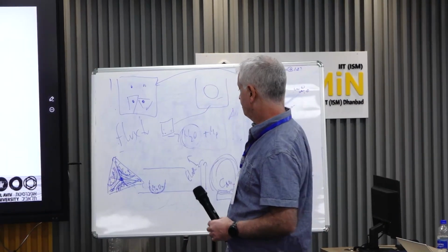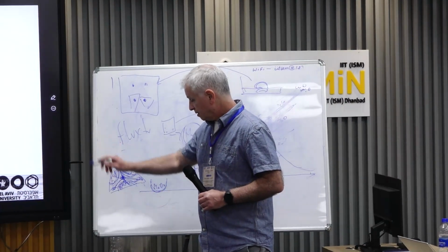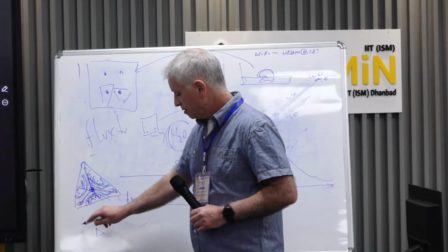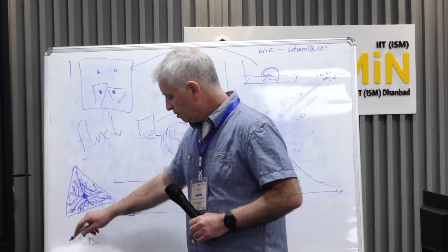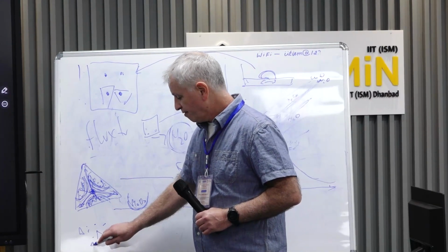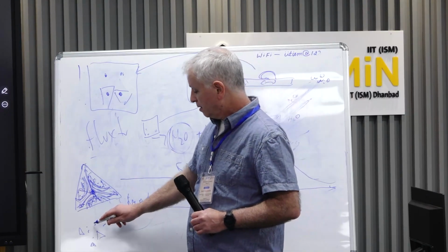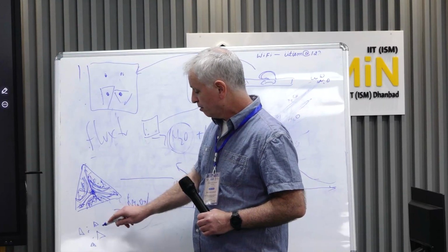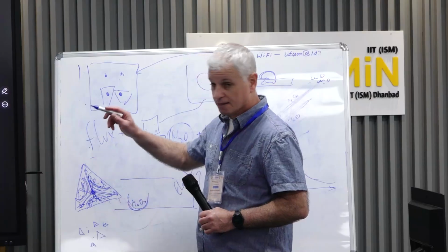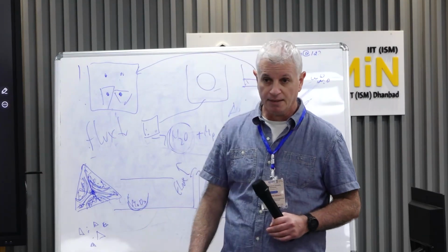So why? Because we start the nucleation, let's say in this case, domains. So you have carbon, you have some nucleation, you have some very defective domains, and you have carbon. The carbon induces nucleation by itself, right? Like the seeding of nucleation, and therefore it creates defective domains.